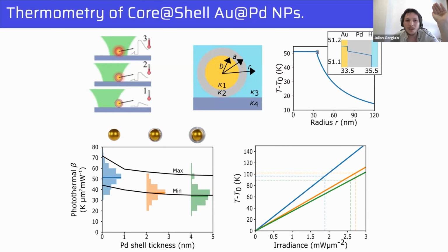No, I mean, the histograms that you see there, it's a dispersion because we have many particles. But the black solid lines is what our theory says it should be. And the reason why we have two lines, one that says min and one that says max, is because in the literature, in the papers, all the coefficients that we need to put into the equations are not very well defined. So if you want to be quantitative in the prediction, it's very hard because you don't know exactly your system. You don't know what to model. That's why I think it's very important to have experimental methods and to measure it.